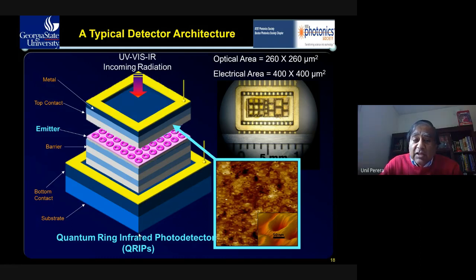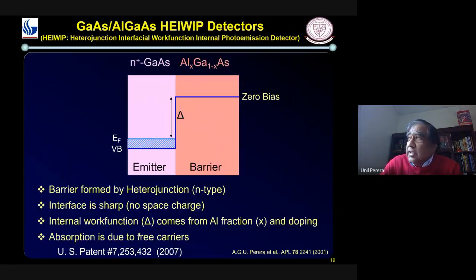That means you cannot change the photon energy needed for the absorption. That in turn says that your infrared detector will have some specific wavelength. So if you want to change the wavelength, one option is you can change the size by converting the dot into a ring. Then you can extend to a longer wavelength. And there is another option by using a dot in a well, putting a dot inside a well. We can get to that in a minute.